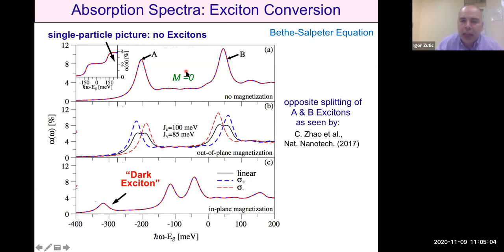If we look at a non-magnetic substrate, no magnetization, then we get, using this Bethe-Salpeter equation, the expected A and B excitons, which I mentioned. If we then go to out-of-plane magnetization, which is the focus of most of the studies, we also see expected behavior: the exciton will split, and the splitting of A and B exciton will be opposite, just as it's seen in the measurements of our colleagues.